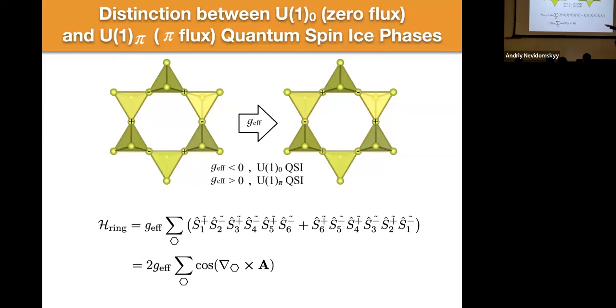Okay? Because this is an arrangement of neighboring tetrahedra in the Pyrochlore lattice, and here we've got 6 tetrahedra. Okay? And if you've got 6 interconnected tetrahedra, you actually close this interior hexagon of connected spins. And so if you do a calculation on 6 or more tetrahedra, you're thought to be capturing a lot of the relevant physics, at least at these sorts of short distances. Whereas if you do the calculation at less than 6 tetrahedra, you're leaving out one or more of these, and so you don't have whatever physics would come from the hexagons.